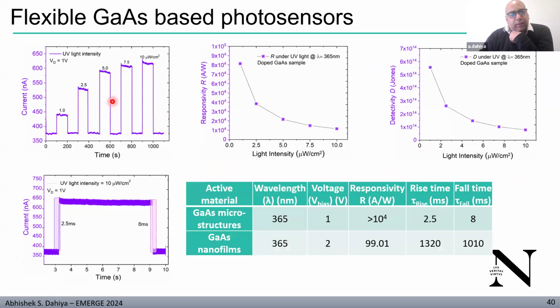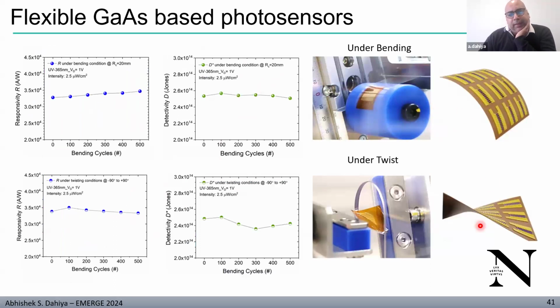A few characteristics we have on this slide for UV light sensing. The interesting parameter is the response speed of the sensors, which was in milliseconds, and also the recovery time was quite fast, and the responsivity of these devices can reach up to 10 to the power 4 ampere per watt. We have also tested them under bending and twisting, showing the robustness of these devices. These are the responsivity and detectivity plotted against bending cycles, up to 500 cycles, for which we used equipment to put our devices on different radii of curvature of the rollers and twisting angles. We have shown that the devices are quite stable under bending or twisting conditions.